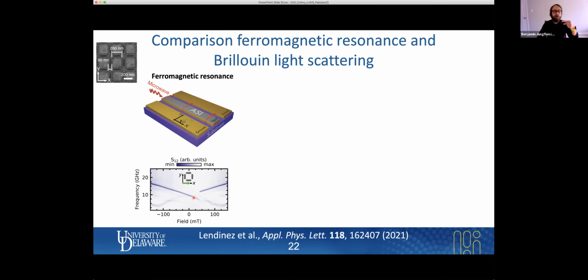Why is that? Well, the magnetization lies in the direction of the elongated elements, which are parallel to the external field. That's the easy axis. And therefore, the microwave magnetic field, so the Ørsted field here in red, is perpendicular to the magnetization. So we have a maximum torque, and we can effectively excite the dynamics and detect them. So these lines are coming from the horizontal elements.